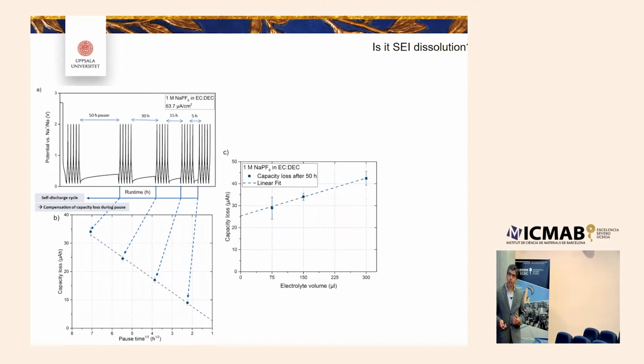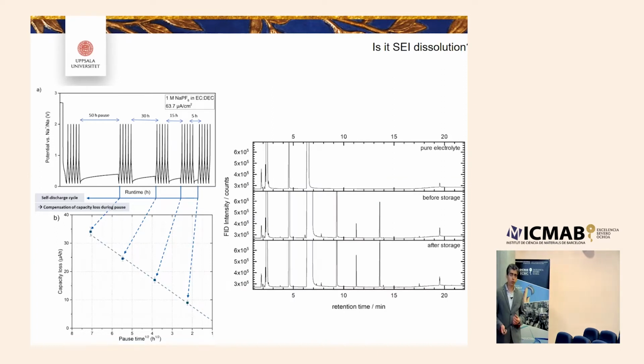We also did some mass spectroscopy measurements. I'm not going to go into detail of all the peaks, but briefly, if you compare the pure electrolyte to this sample in the middle, labeled before storage, you can see that the cycled electrolyte has more peaks as we expect. There are more things formed in the electrolyte.